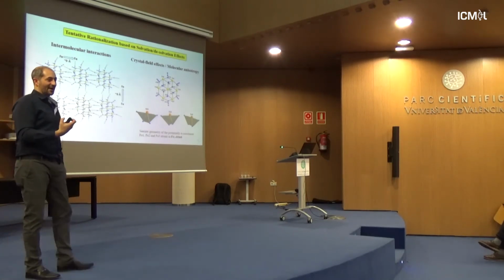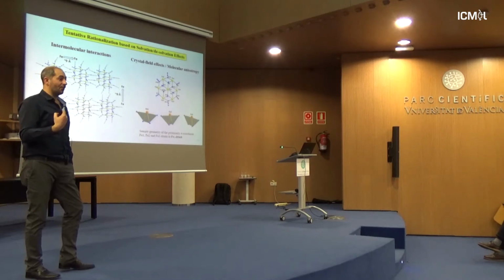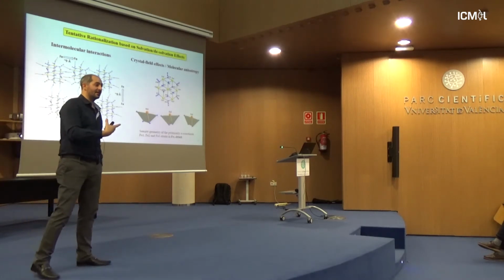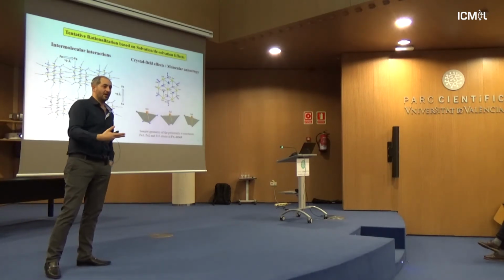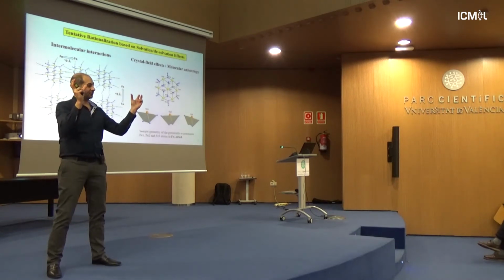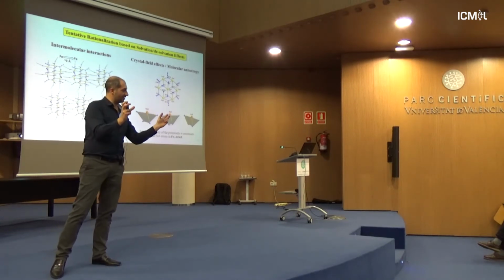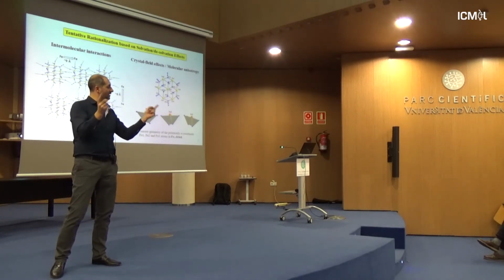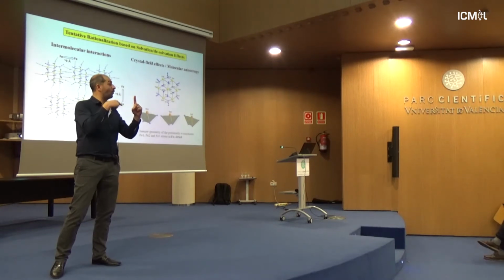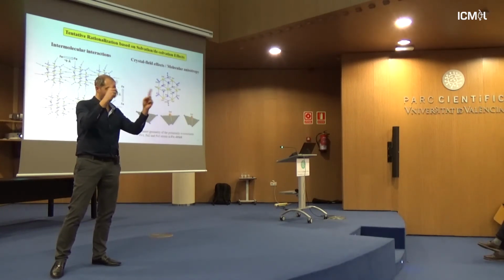Now, a third scenario comes from maybe the difference in the magnetic anisotropy. If you have two relaxation processes, but at different temperature, provided that the molecule is the same and the spin is the same, then the only way to explain the difference, okay, one of the ways to explain the difference will be what? By changing the D, the magnetic anisotropy.